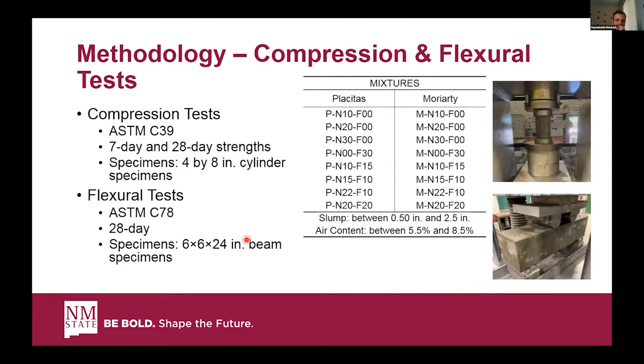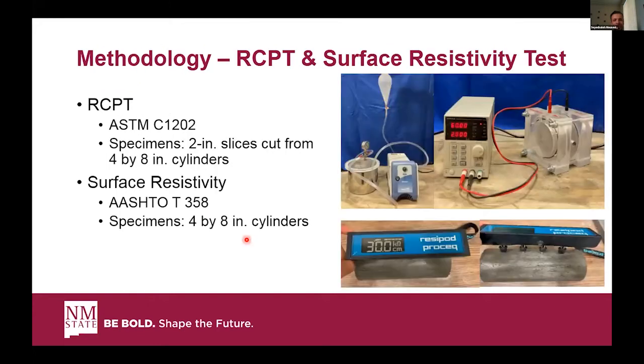In another part of this project, as I've already mentioned, some mechanical tests were conducted and other durability tests. For the mechanical test, first we have conducted compression tests based on ASTM C39 and 28-day strengths were measured for 4x8-inch cylinder specimens. We have also conducted flexural tests based on ASTM C78 and 28-day strength were measured for 6x6x24-inch beam specimens. For RCPT, we have used ASTM C1202, and for the surface resistivity, we have used AASHTO T358, and this test was performed on 4x8-inch cylinder specimens, as you can see in the figures.